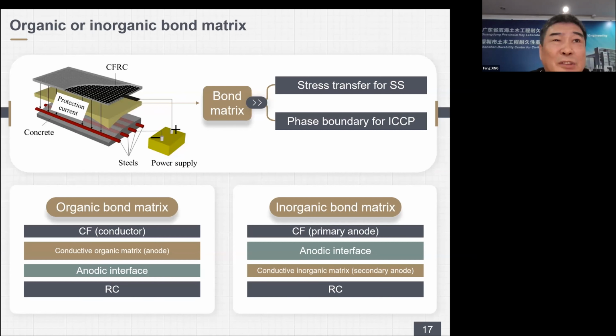However, the mechanism of epoxy resin and the cementitious matrix in this case are totally different. The electrode reaction is a process of charge transfer between the electrode carrier and the ion carrier at the phase interface. Epoxy resin doesn't provide ion. Therefore, even with conductive resin, the reaction will still occur at the interface between concrete and the resin. In this case, the CF works as a conductor, not anode. Considering durability of epoxy resin is not good, anode degradation makes the service life even shorter.